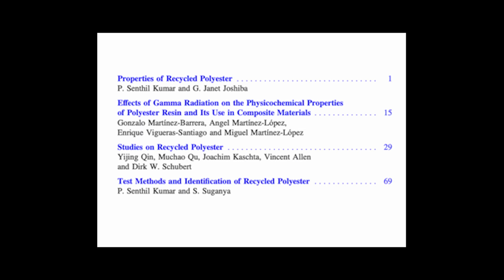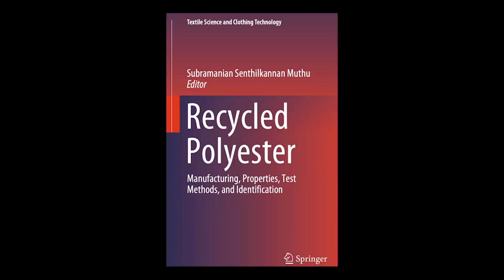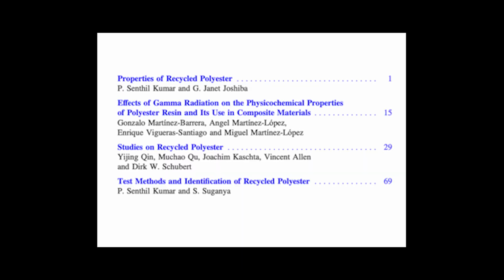For instance, remember that contaminated recycled batch, rPTA, from the spinning study? Yeah, the one that degraded badly. Its TGA curve showed it had the lowest decomposition temperature, starting to break down significantly around just 365 degrees Celsius. That low value signaled its inherent weakness and instability compared to the cleaner rPET or the virgin materials. Okay, so TGA checks the decomposition point.